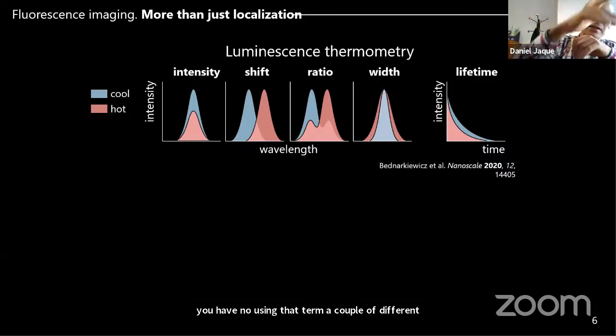And also the decay time, I mean the fluorescent lifetime of the nanoparticle. If the fluorescent lifetime of the nanoparticle depends on the temperature, by recording the fluorescent decay time, you can measure at which temperature is the nanoparticle. And what is super important here is that you are using light to measure the temperature. You are not using a thermocouple that is in contact with your animal, or a thermometer that is inside a living cell. You are using light. It means that it's a contactless method. It's like a wireless method, okay?